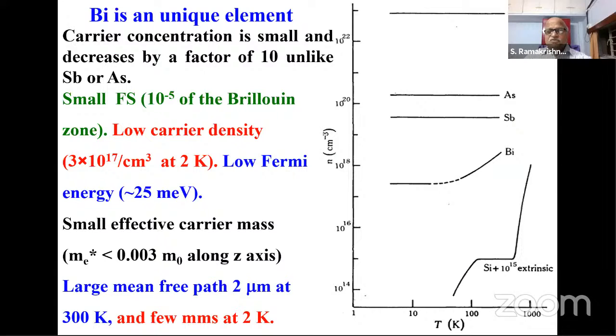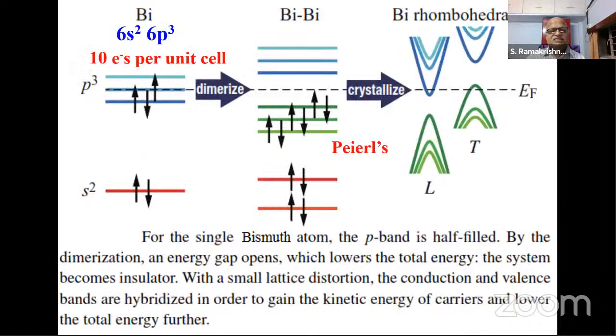So imagine if you have a completely large mean free path system, like say 5 millimeters in bismuth, which means the electrons are ballistic. Electrons are not having any collision in that material. So to measure transport and so on, it is a huge, huge task, because most of the contribution is coming from the boundary scattering, not inside the material. So it is really difficult to determine its absolute resistance of the system. The intrinsic boundary resistance you can compute. So that is another puzzle. I mean, that is another interesting thing about bismuth. Silicon, of course, has a carrier concentration difference, but that is because it is being doped by other elements.